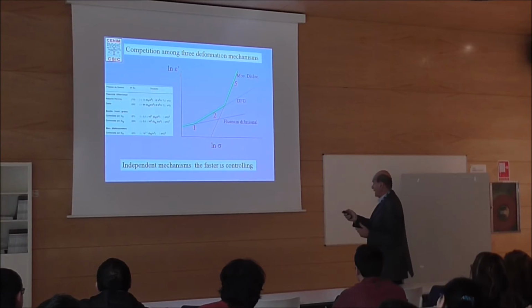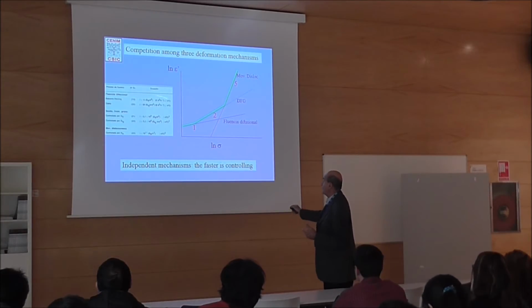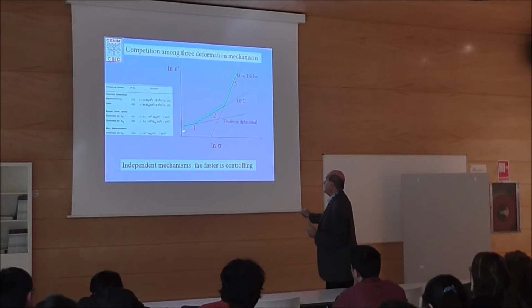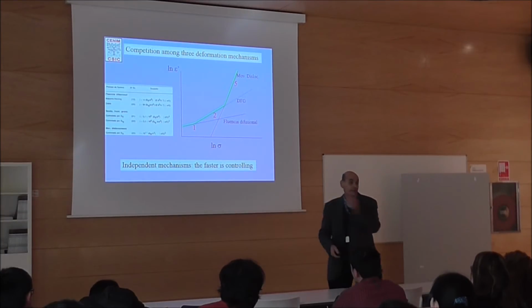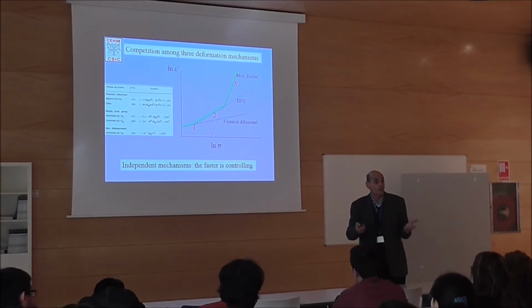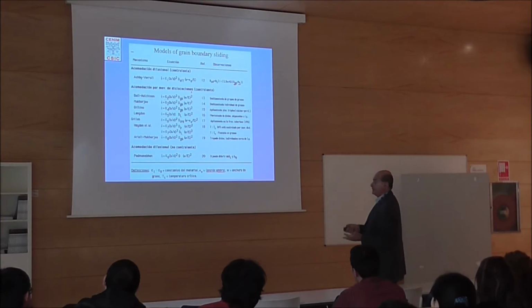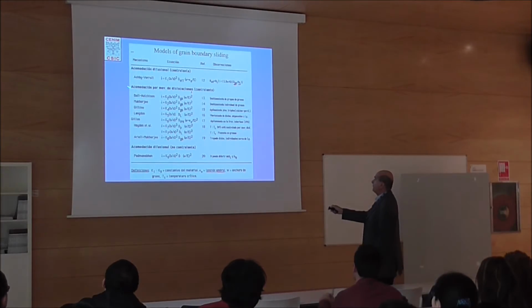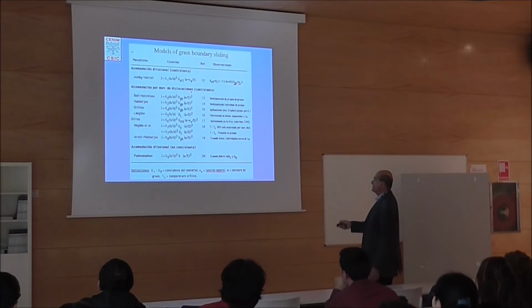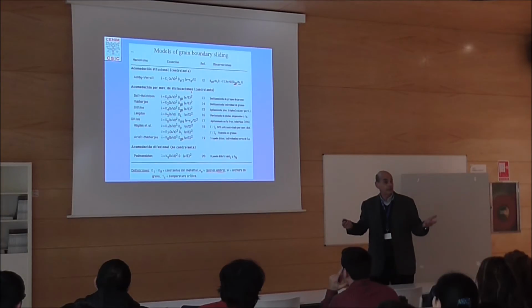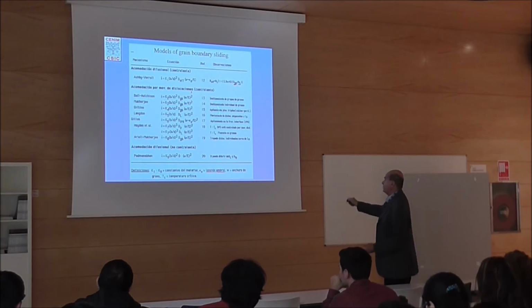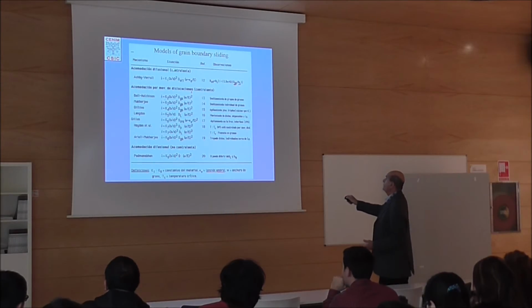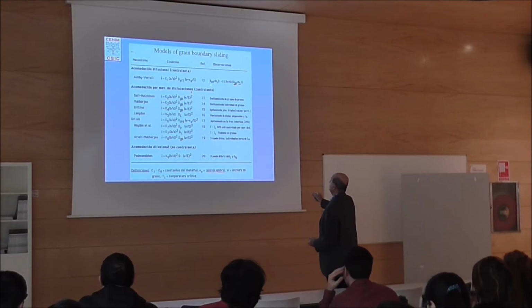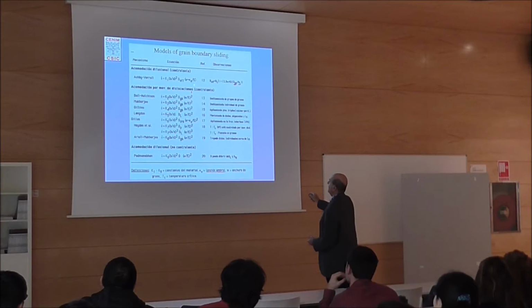Or in other words, you have the equations for diffusional flow, you have the equation for slip creep, and these are equations that Sherby and myself used at Stanford to correlate the data. And why doesn't it exist for grain-boundary sliding? Because all these people, Ball, Hutchinson, and these are very well-known scientists, gave equations like this, but with these K constants that are empirical. So nobody knew which one of these 10 equations was to be used. Only Ashby and Verrall used this equation, but this equation is for n equal 2, n equal 1. Here, n equal 1 after some stress, of course.